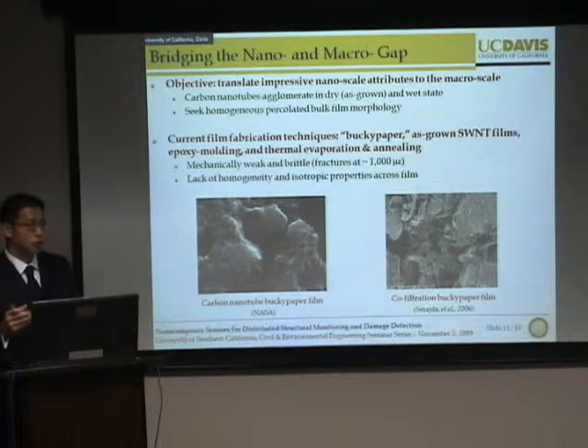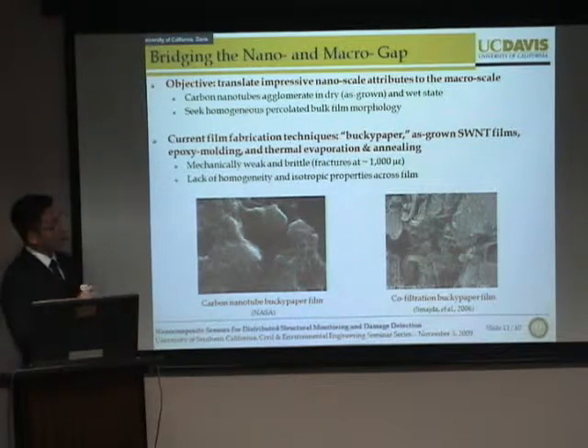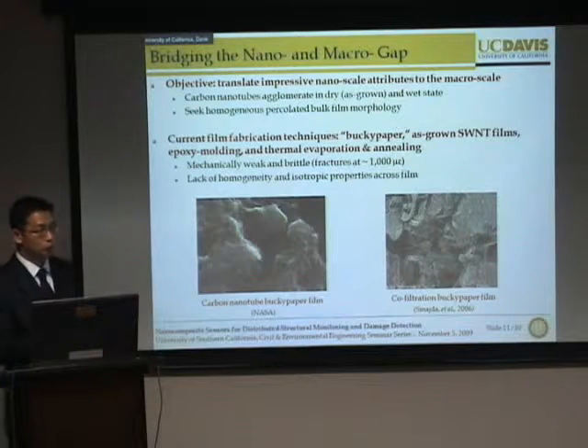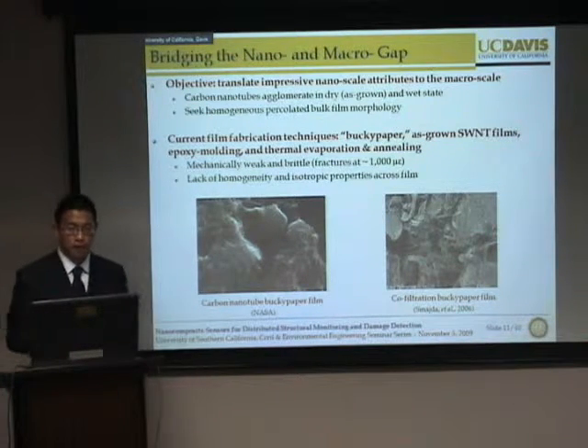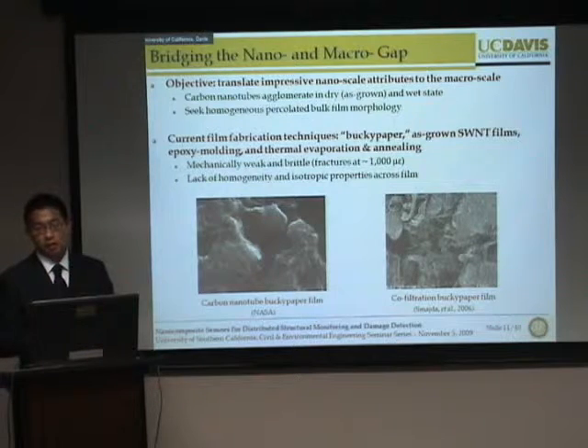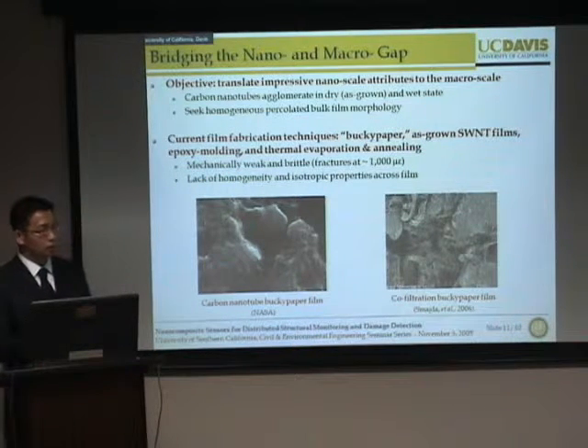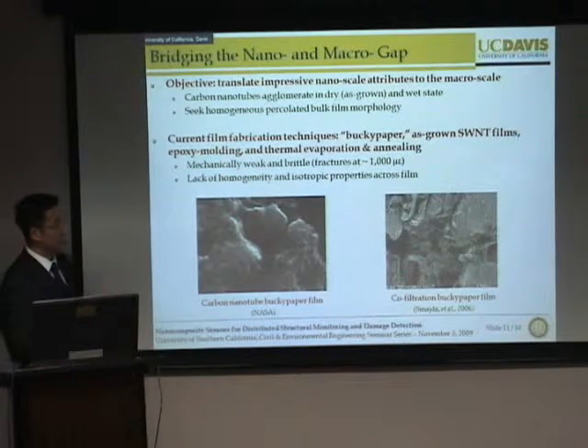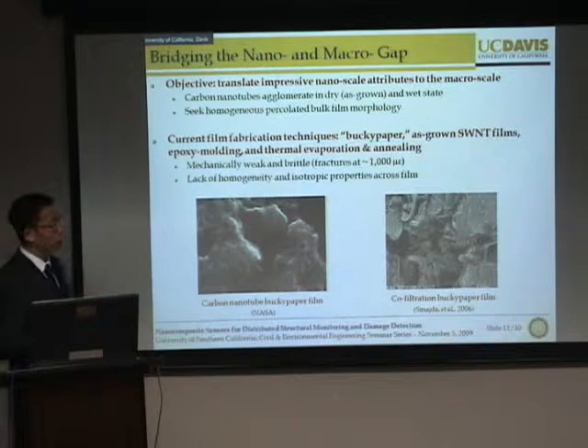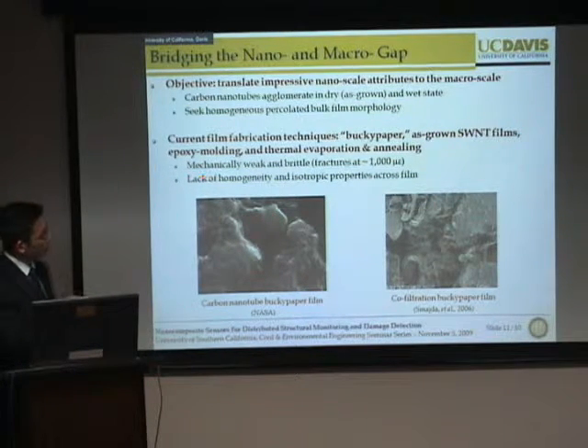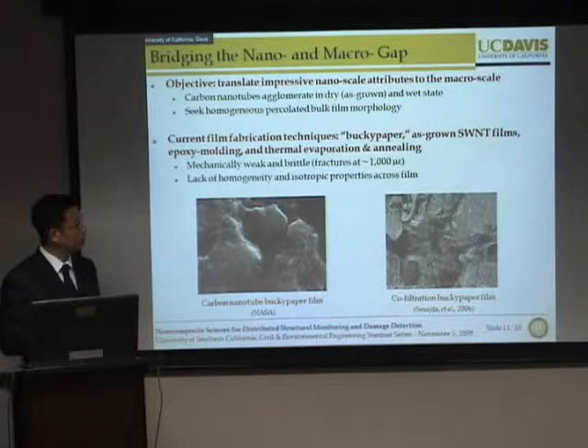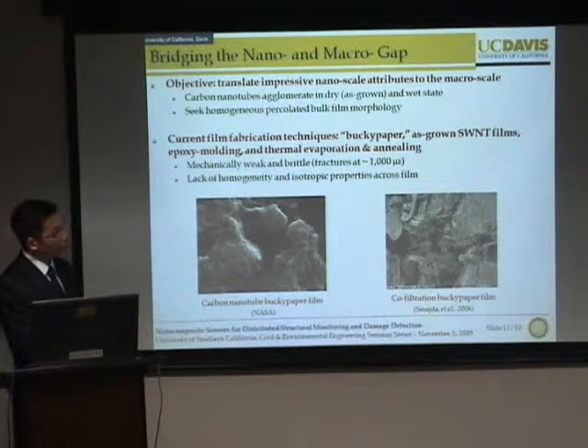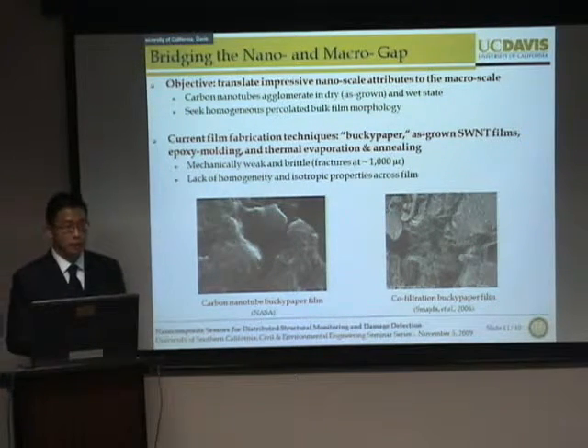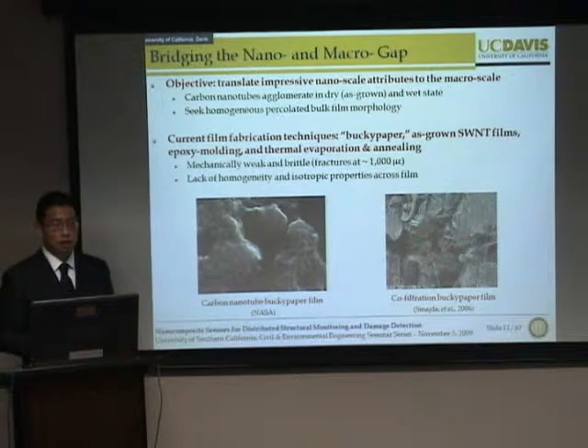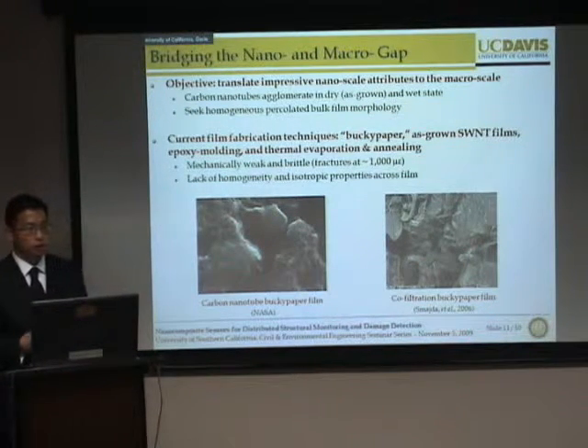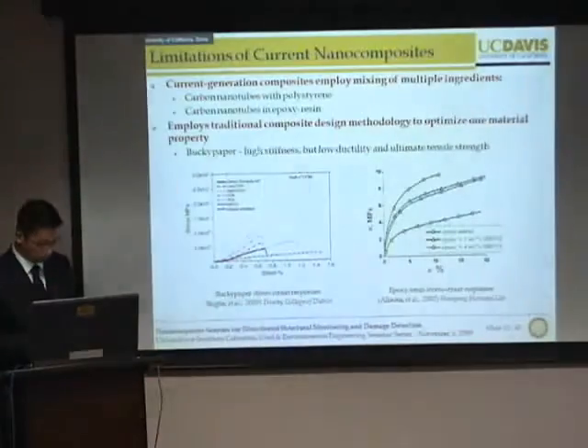That is, people are just trying to forcefully embed carbon nanotubes within some type of matrix system. And it is because of this lack of nanoscale and microscale control that the final material properties of the composite system are essentially quite poor. In fact, if we consider the mechanical properties of Bucky papers, they're quite weak and brittle and fracture at just 1,000 microstrains. And because of this lack of control, the material is also very inhomogeneous and non-isotropic.